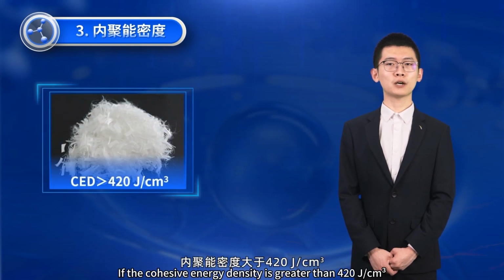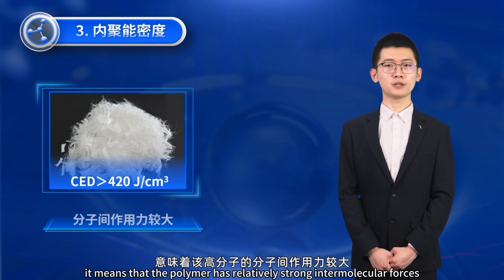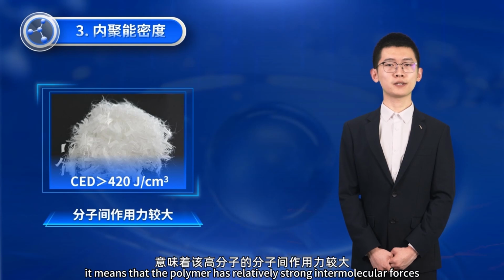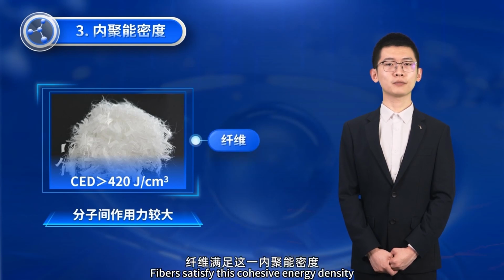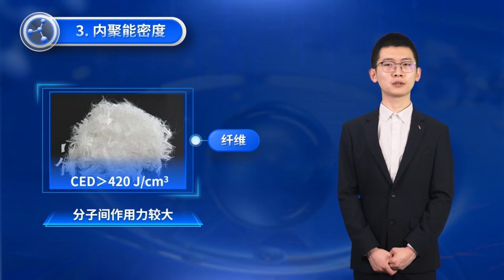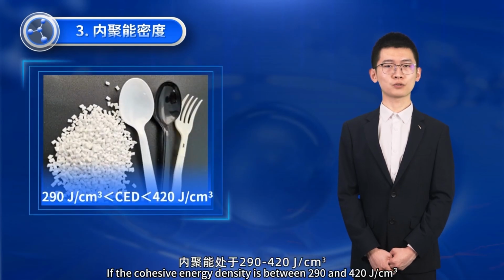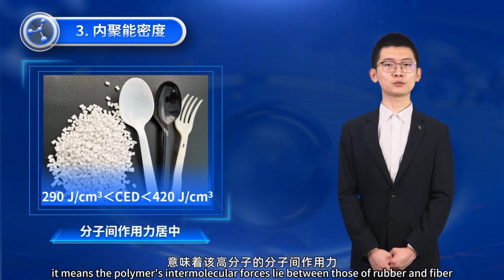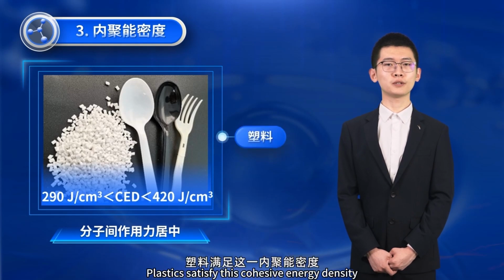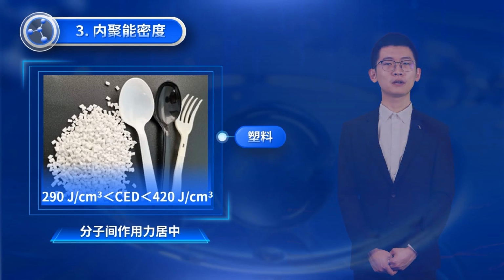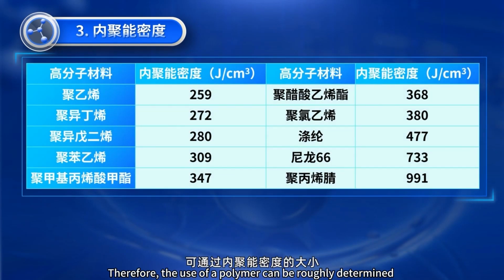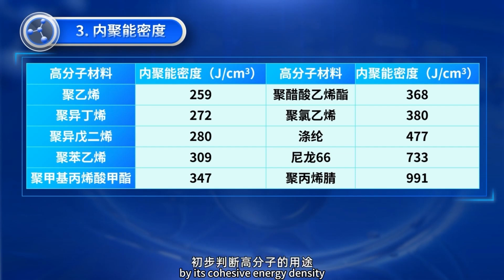If the cohesive energy density is greater than 420 joules per cubic centimeter, it means that the polymer has relatively strong intermolecular forces. Fibers satisfy this cohesive energy density. If the cohesive energy density is between 290 and 420 joules per cubic centimeter, it means the polymer's intermolecular forces lie between those of rubber and fiber. Plastics satisfy this cohesive energy density. Therefore, the use of a polymer can be roughly determined by its cohesive energy density.